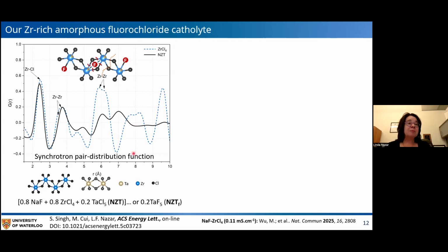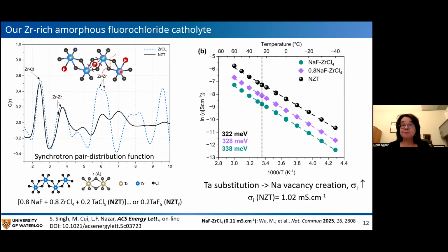And so we think that what we're forming by this reaction, which is at room temperature, but probably slightly warm because of the ball milling, is that we take the parent structure of the zirconium chloride shown here, and effectively the fluorination breaks these chlorine-chlorine edge-shared bonds, and we probably form linear fluorine arrangements between the metal centers. This is either the zirconium or the tantalum, and so effectively we open up this structure. But it's obviously oligomeric and probably short chains. It just spans a few metal centers because of the lack of long-range order. So our conclusion is that we have these sort of short oligomers of these metal halides.